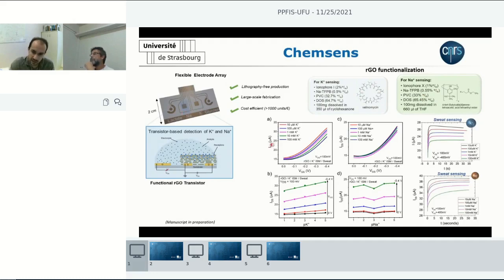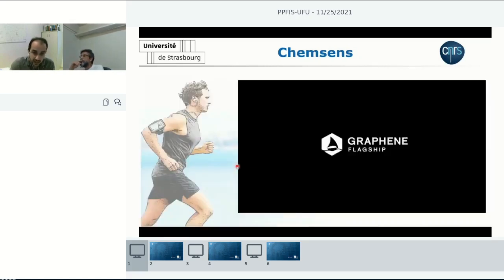for sodium. Here I will not go into the details, but you can measure the current, the transfer curves of the device, both continuously or as a function of time, and the functionalized transistor is sensitive to different concentrations of the ions of interest. And we did this because we were interested in developing a wearable sensor for detecting chemical species in the sweat of athletes. And this is what we did within this project called Graphene Flagship.